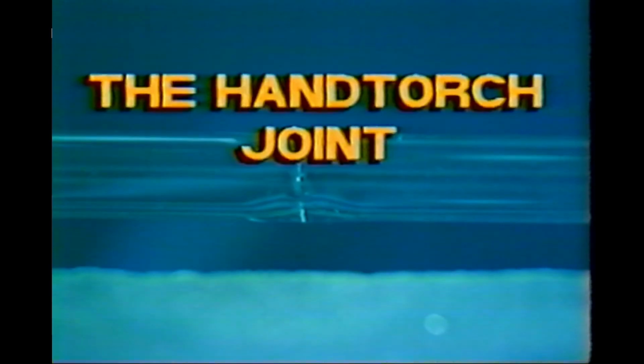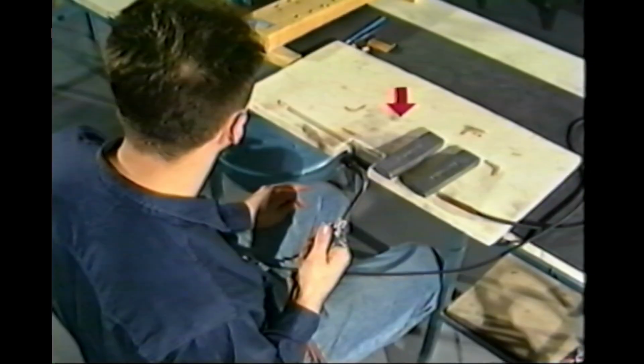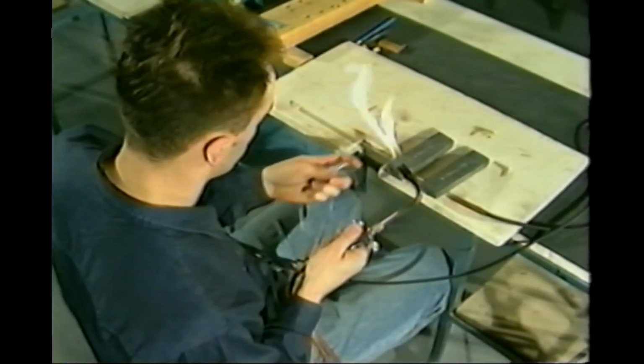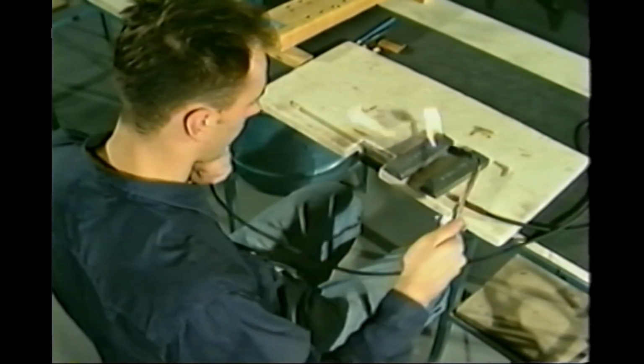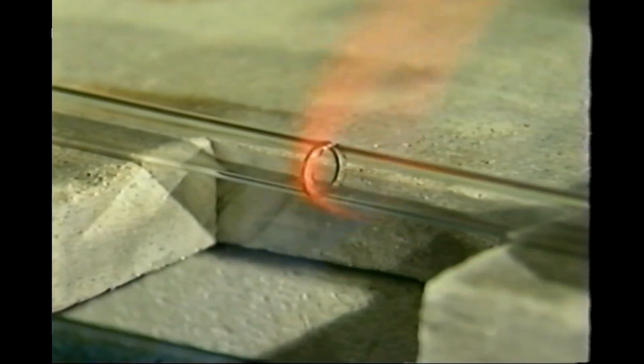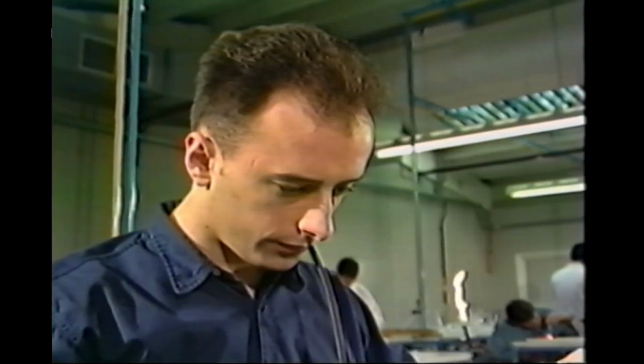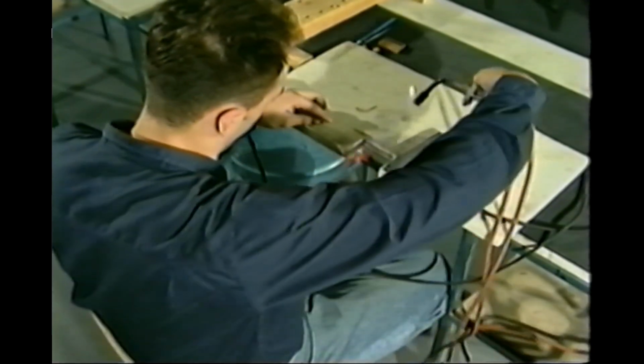From the bending exercises, we now move on to the hand torch joint or splice. Place the cutout block on the bench top. Set up the cork tube on the left-hand side and weight down the tube with the blow tube attached on the right-hand side. Set up a medium-sized soft flame on the hand torch and carefully preheat the two open ends to be joined to prevent thermal shock cracks. Grasp the tube on the left side and move it towards the other open end until the two open ends are 1 millimeter apart.